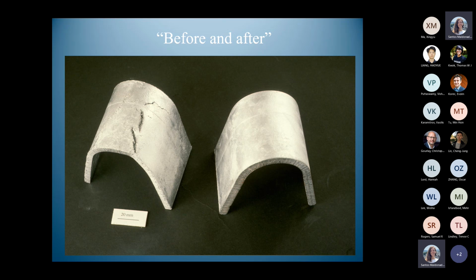It's the randomness that tells you this is due to the randomness in the way the liquid jumped and splashed inside the mold to create these cracks in the liquid state, which then get solidified in. And this one was done less than 0.5 meters a second, so that was safe, no cracks.